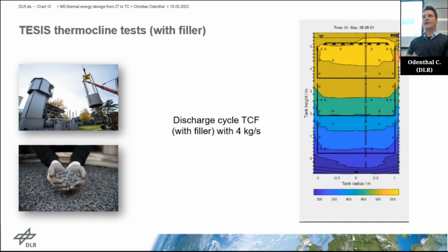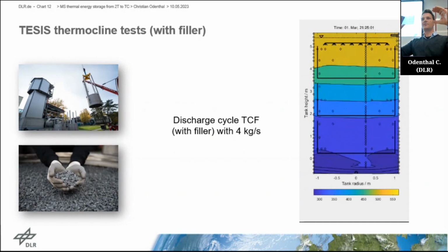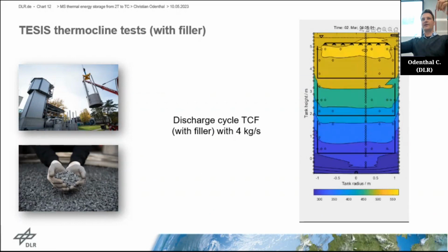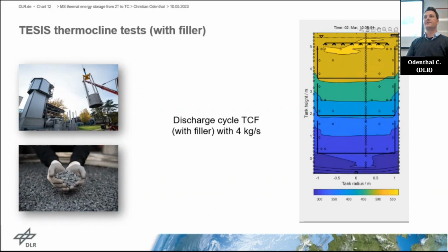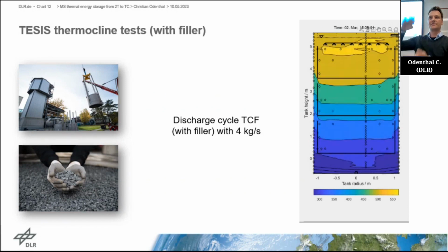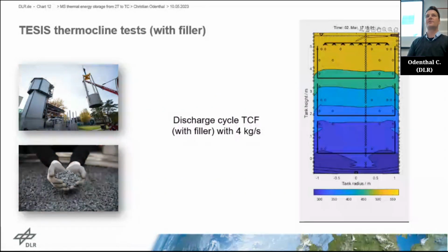What you need to bear in mind is that you need to extract this thermocline region a bit. The more you extract, the closer you come to the initial situation where you start over with a freshly built up thermocline. That would be the ideal situation, but in that case, you have to think of your exit temperatures of the storage system. If you extract the thermocline, for example, during the discharge process, then your outlet temperature goes down.